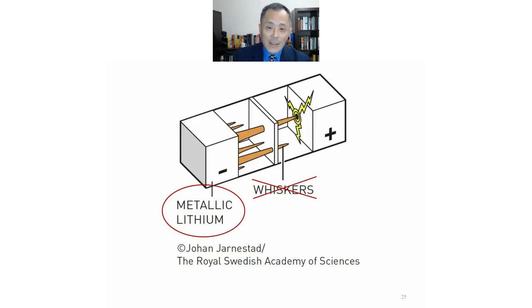My next example is the measurement of mechanical properties of metallic lithium. Lithium was proposed in the original invention of rechargeable lithium batteries, but there's a problem with dendrites or whiskers. Currently, there's a renewed interest in using lithium as the negative electrode because if it can be done, there will be no additional weight from the host species, such as carbon or silicon. So there's active research on how to either prevent dendrites from forming or block the dendrites from penetrating through the separator.